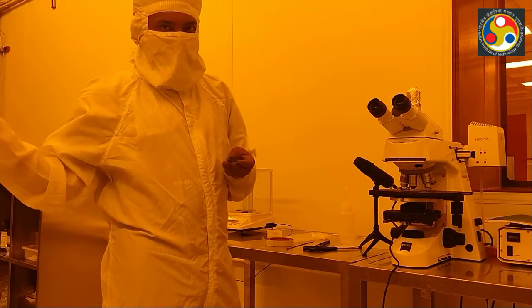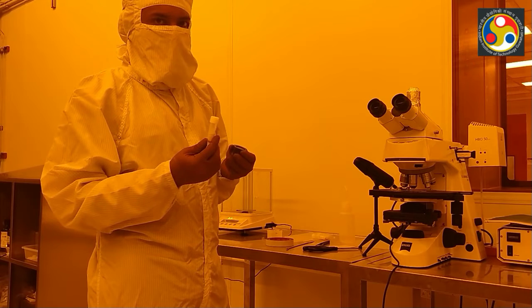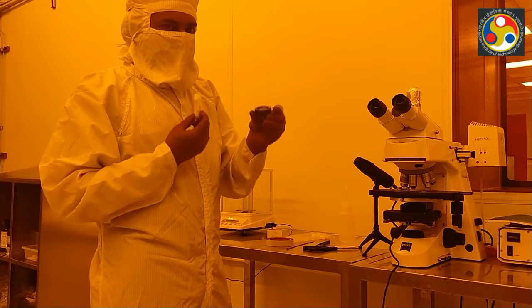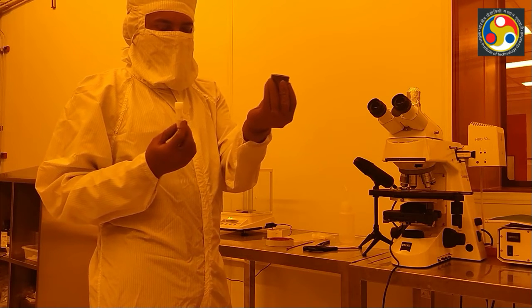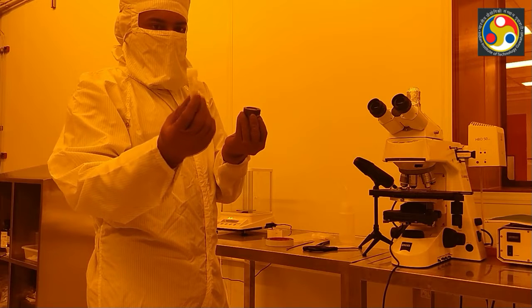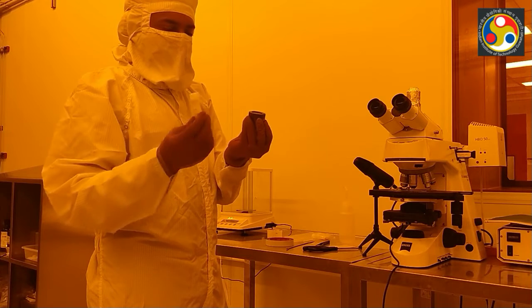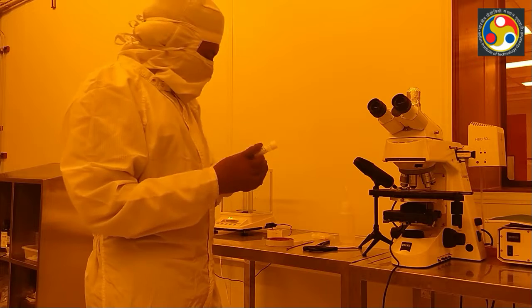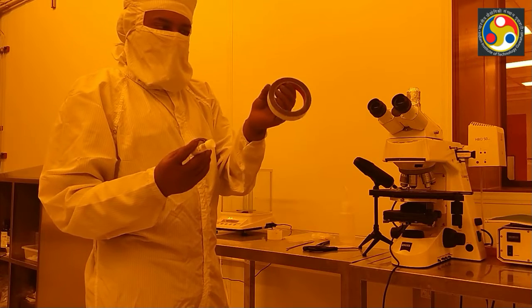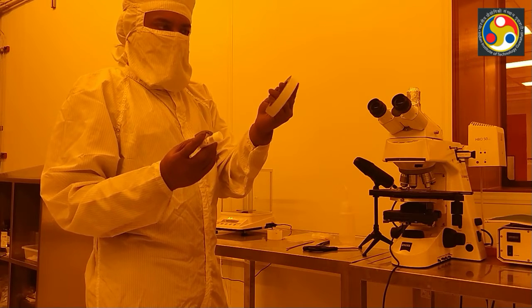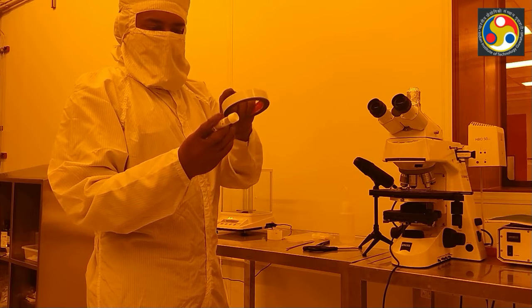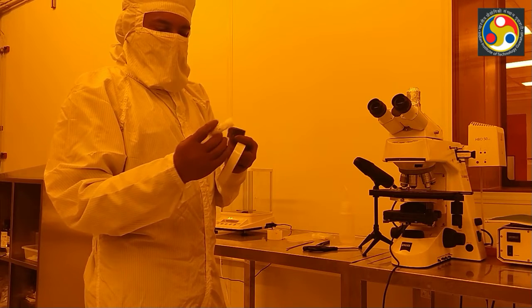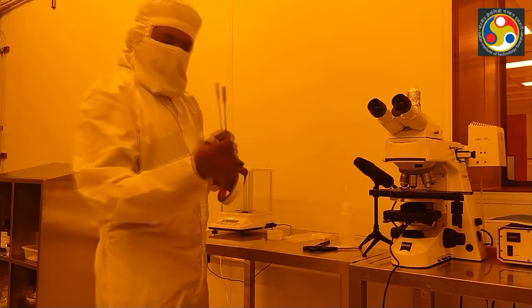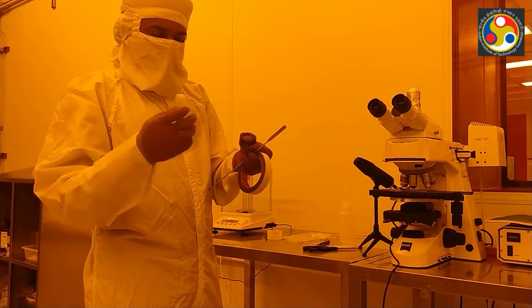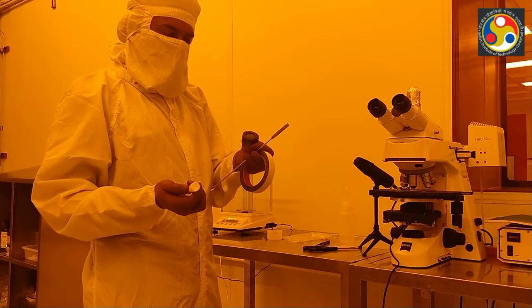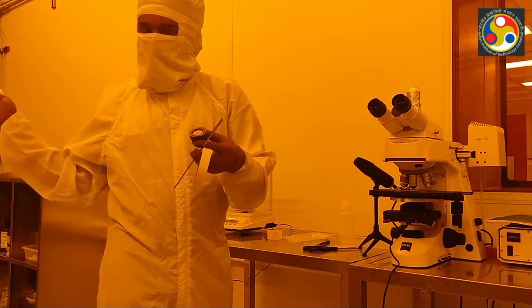So I have an instrument which is called field emission scanning electron microscopy, and this is the sample holder. I will spread this sample of my nanoparticles into this sample holder by using this tape. This is a conductive tape, conductive carbon tape. I will paste this carbon tape in the sample holder, and then I will use this spatula to spread this sample into this sample holder. Then we will do the coating.